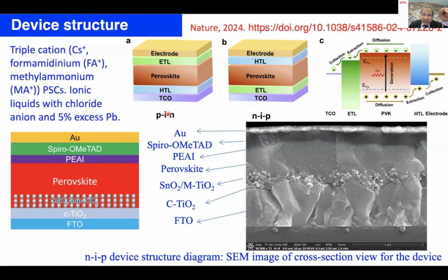In the other configuration, PIN, we change the charge transport material from the electron transport material to the hole transporting material. And here the condition is the hole transport material has to be transparent. So this gives you a lot of design opportunities to tune the properties of this hole transport material. Then the light goes to the perovskite, and on top we have the electron transport material. So these are the device configurations. So let me give you the efficiency.